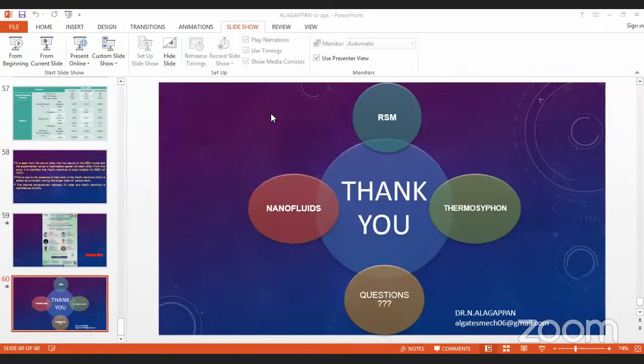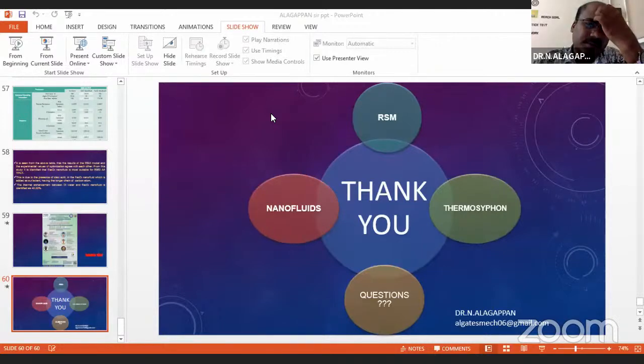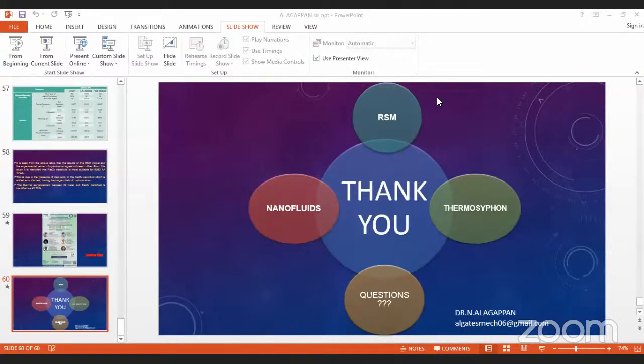Is there any specific reason for using this container material? Because the general material is copper, right? So, does using this container material increase the efficiency of the heat pipes? Yeah, definitely. If you try only with copper, my research work gives some percentage of improvement. While using copper, the same Fe3O4 nanofluid gives only 20% improvement in efficiency. Instead, I use the Fe3O4 nanofluid with the aluminum container material, and I get 43.3%. So that's the difference. Okay, sir. Thank you.